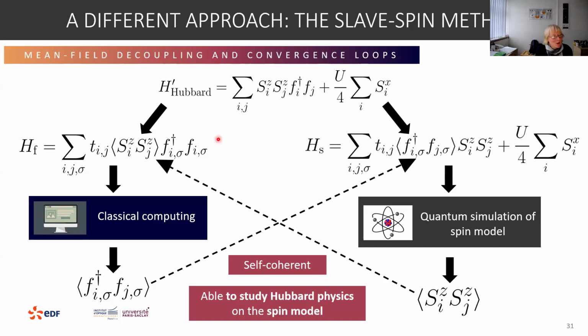Okay, because it's a very nice model and it maps very well to the spins. Exactly, that's why we have chosen this one, because we avoid any kind of transformation. Yeah. No, so it looks very nice, but then I'm looking at this cycle round and going, okay, that's great, but in our case it converges, but often it's the case that you can tell numerically that it's converging. Right? Yes. Even if there's no proof that in principle it has to. But also there's how fast it converges. I mean, how many iterations do you find you have to do? It depends on the size of the system, of course, but I mean, 20 iterations are enough in many cases, so it's not that big.